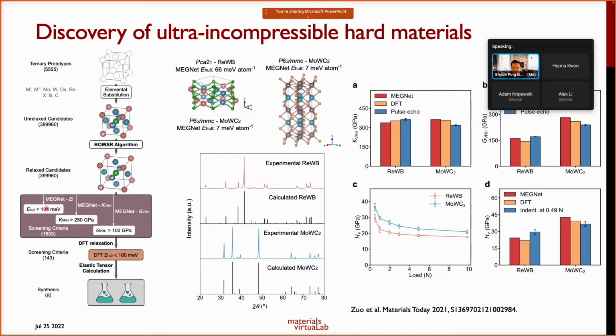So we want something like the Ehull has to be less than 100 meV per atom for it to be stable. We predicted the bulk modulus. The bulk modulus has to be sufficiently large because we want hard materials, and the shear modulus also has to be sufficiently large, right? After we apply this simple screening criteria, from all our 400,000 crystal structures, we can whittle it down to about 1,600, which is a good enough number for us to start to do DFT on. And then finally we do DFT relaxation. We then screen using a DFT Ehull, and we get about 143 candidates.